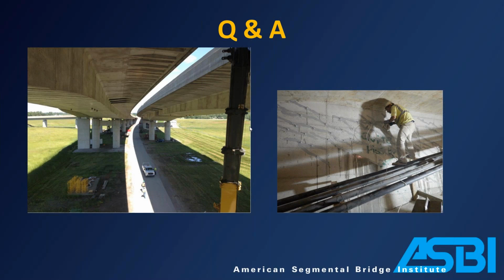If you're going out every inspection cycle, or in between inspection cycles, and you're seeing three or four more new cracks, or the cracks are getting wider, or you're seeing anything move under traffic, to me that's going to trigger structural health monitoring, or getting another group of experts out to do a deeper dive into why that's happening. So I would say crack propagation is going to trigger me to do structural health monitoring 24/7, so I can keep an eye on that thing.